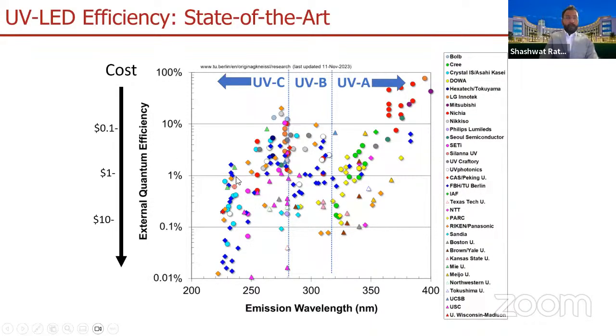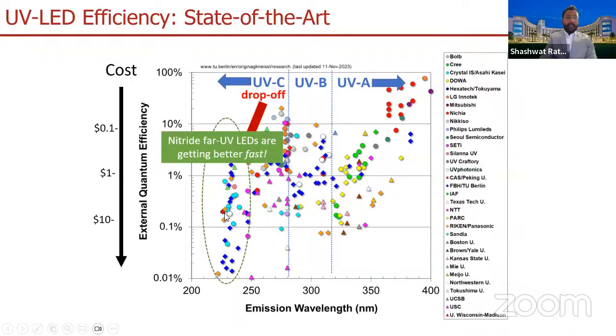So the technology is far from commercial use, because at least we would need about 10% to make a proper use case of this technology. So there are a lot of challenges in this technology that need to be overcome, and this is what our endeavor is moving forward. So to basically avoid this drop off and make highly efficient far ultraviolet emitters in this range, right? But nitride LEDs are getting better fast, as you can see. In the previous few years, the quantum efficiency was below 0.1%, and it has gone up to single digit percentages already. So obviously there is light at the end of the tunnel here.